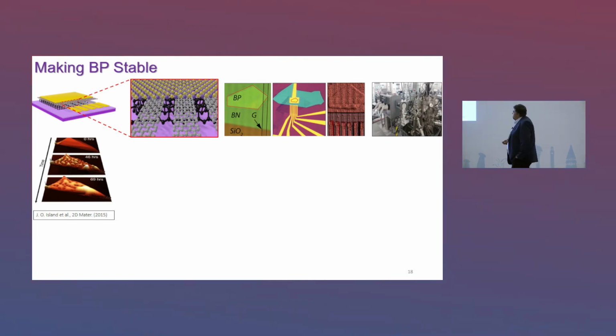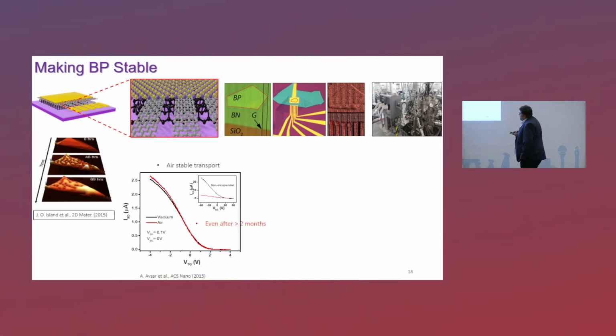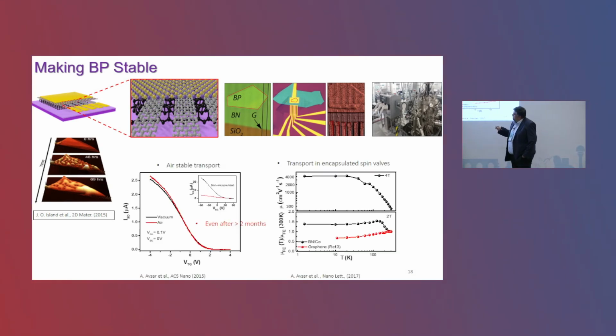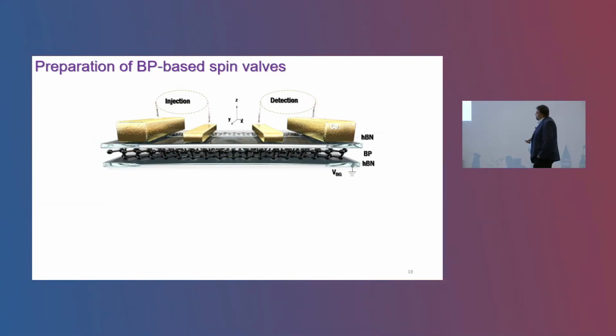combined with the MBE system. And we use graphene as a contact, so we could show that the material works identically whether you measure in vacuum or in air, and it works for at least 90 days without any issue. And the mobilities that we could observe are already up to 4,000 at low temperature. After learning how to make this material air stable, for which you really need to do everything in the glove box environment, once you develop an effective encapsulation process, you can take it out and do all the fabrication outside of the environment.